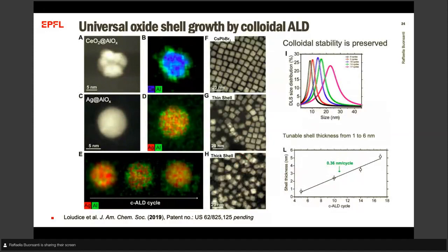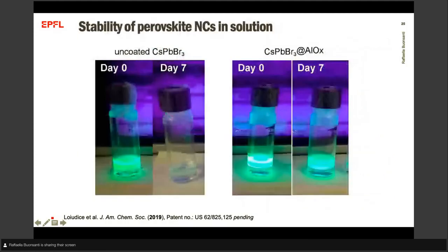What is important is that we were able to grow this oxide shell of many different materials, including metal oxides, metals, and perovskites. And we could use a technique such as simple dynamic light scattering to observe the growth of the shell, which we could tune below 0.36 nanometer per cycle, because 0.36 corresponds to the aluminum-oxygen bond. So this is a layer-by-layer technique, and that's why it's a really precise tuning of the shell. Again, we did gain some stability of this perovskite in contact with water.